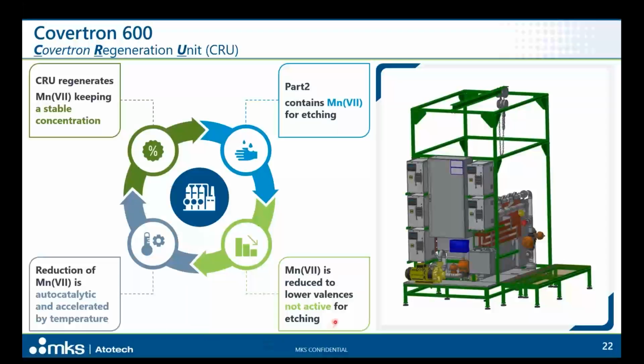And what this unit that you can see here on the screen will be responsible for is to regenerate this manganese, which has been reduced to lower valence, and to react it back to manganese 7, keeping its concentration stable and allowing the system to continue oxidizing the plastic resin.